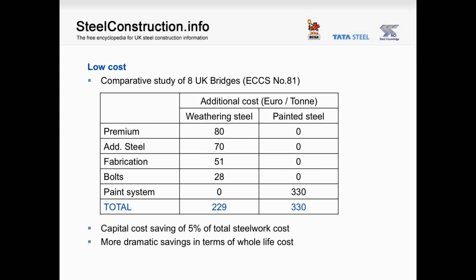Whilst the material itself is slightly more expensive than ordinary structural steel, and also there are additional costs for the bolts and the fabrication, if you add all those up together, it comes to less than what you'd save from eliminating the paint system. So overall, weathering steel is about 5% cheaper than ordinary structural steel in terms of fabricated and erected steelwork. This was demonstrated by a comparative study of 8 UK bridges that was published by ECCS in their publication number 81. And you can see the results in the table. So 5% difference, not a great deal you might think. But when you start to think about whole life costing, there are huge savings for weathering steel, because not only are you eliminating the direct costs of the maintenance, you're also eliminating the indirect costs of the traffic delays.